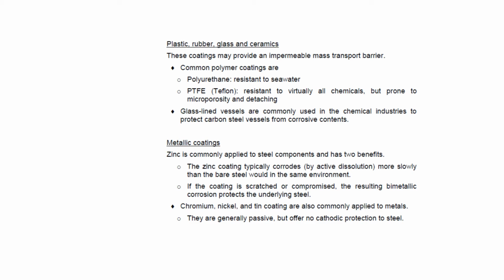We also have sometimes metallic coatings. Zinc is the one which there's a really good ability to apply it to all sorts of components, so that we now expect in the auto industry car parts surely should come coated in zinc if they're steel parts to protect them from corrosion. And this obviously provides both a mass transport barrier that stops the environment touching the steel. It also provides a sacrificial anode in the case that the coating gets scratched and there is some way that the steel could react with the environment. Then it won't, because the zinc will be a sacrificial anode.